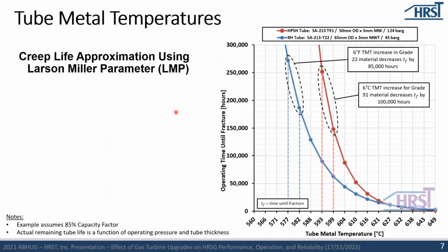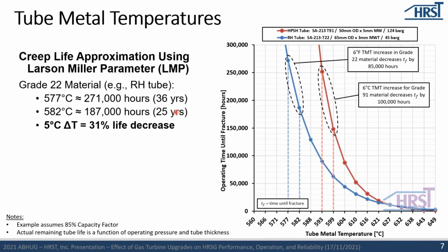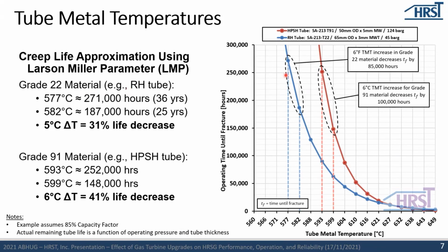One of the more simplified ways that we can look at this without performing a complete remaining life assessment is doing a comparison using Larson-Miller parameter and looking at the creep life approximation for tubes. So I have 2 examples here to my right. The first one is a grade 22 tube, which can typically be attributed to a reheat tube. And you can see here along this curve that the tube metal temperature, by having a very small increase of roughly 5 to 6 degrees C, decreases the lifespan by roughly 85,000 hours, or a 31% life decrease. And this is right in that temperature range that typical reheat systems operate.